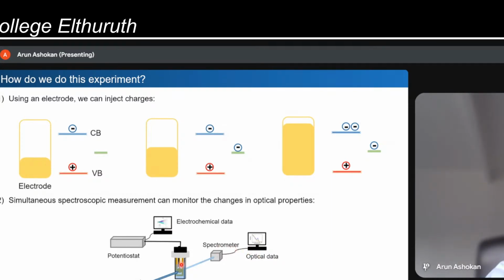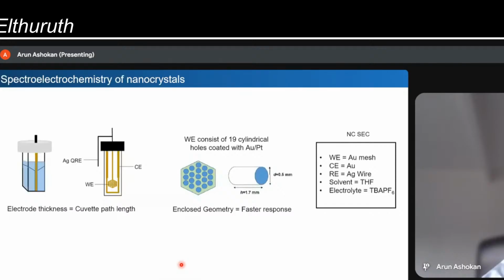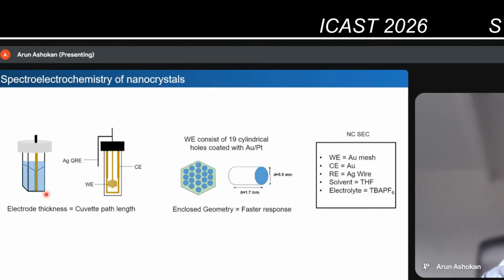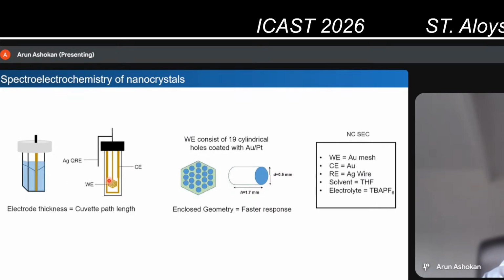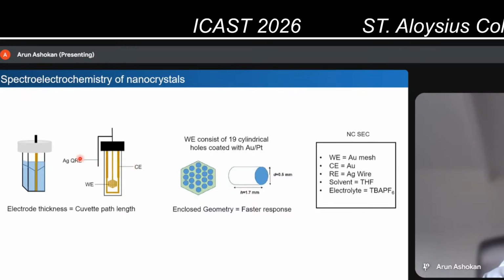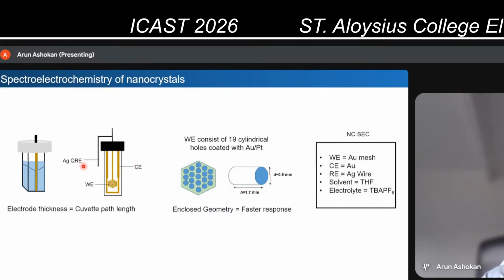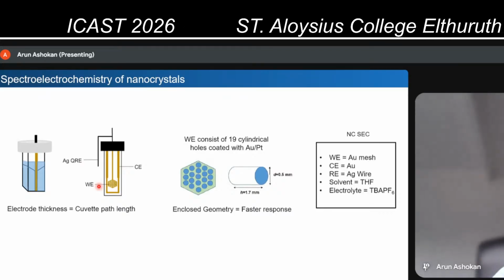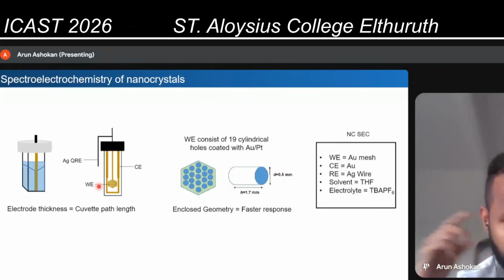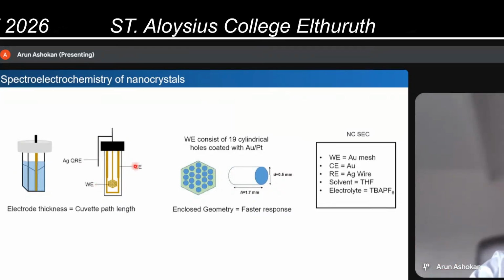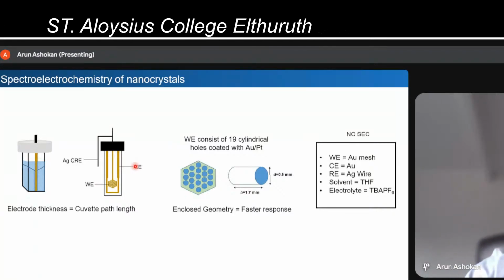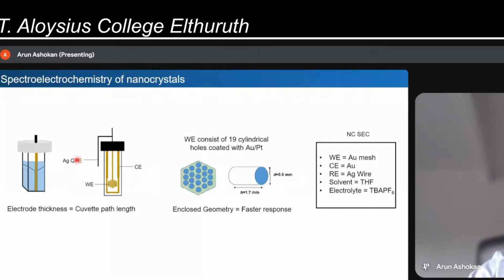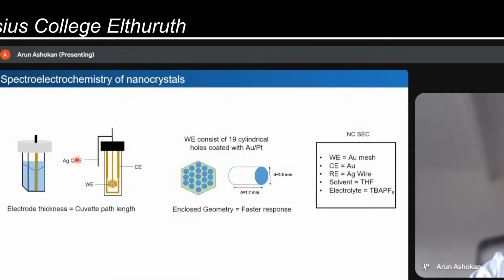Regarding the electrode, I'll briefly show the design of the electrode. So this is the cuvette, and its path length is equal to the electrode thickness, so that we can only monitor those species which are charged. So this is the electrode. You've got a working electrode, a counter electrode, and a reference electrode. Working electrode is where the process of interest is happening. For us, it's the charging of the nanocrystals. The counter electrode just balances out the working electrode. And for measuring the potential, we are using the silver wire reference electrode.